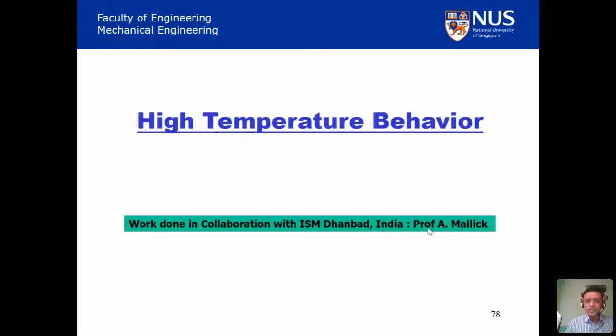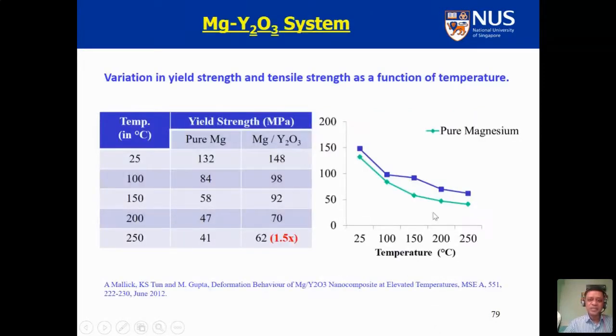Now, since new applications are always going into more and more abusive conditions, you also have to see that your material is better than the normal material. That's how you can sell it. And some of the work in this regard we have done in collaboration with ISM Dhanbad, with Professor Mallick there. And you can see in the graph, the blue is for the composite and the green is for the material which is not a composite. And for all the temperatures from 25 to 250, your composite has maintained an edge.